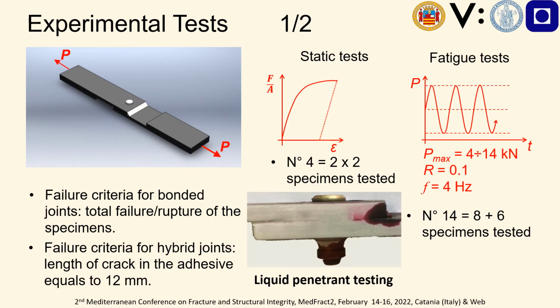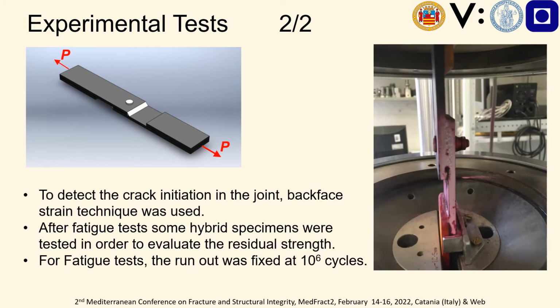And in this picture you can find also the details about the execution of the test, and in particular the load levels, the R parameter, and the frequency of the test. Here you can find the facility used for the execution of the test, and in particular concerning the detection of the crack initiation, the joint was equipped with back-face strain gauges. And in particular, after the fatigue test, some hybrid specimens were tested in order to evaluate the residual strength, and for the fatigue test the runout was fixed at 10 to the power of 6 cycles.